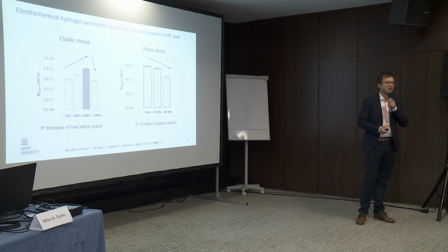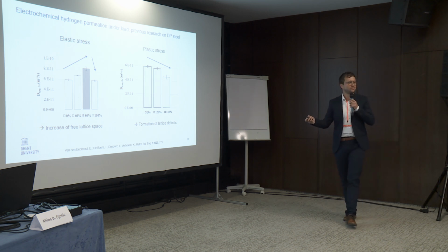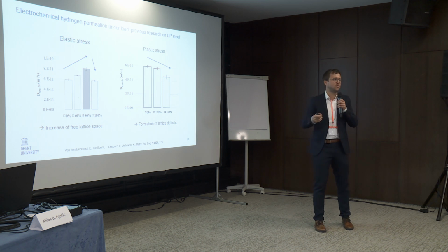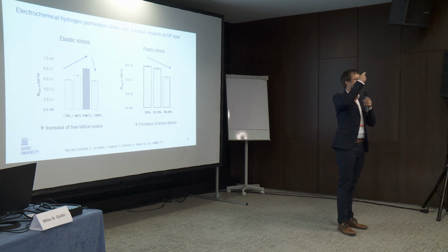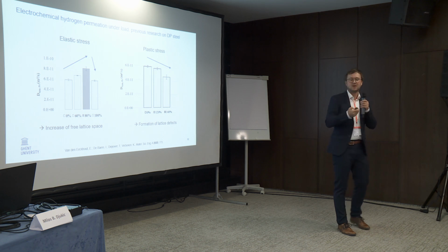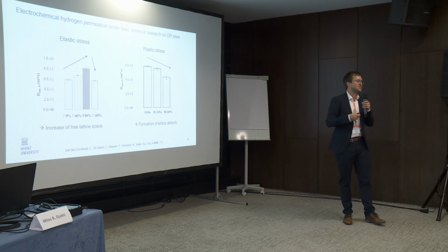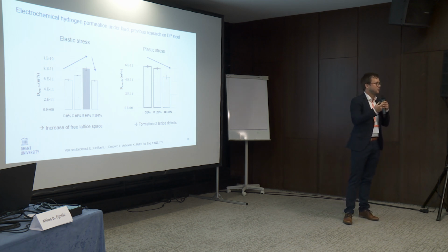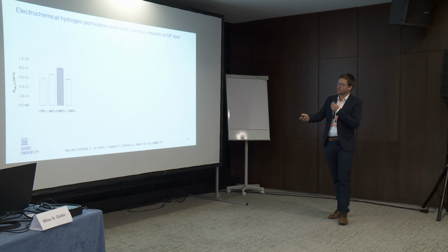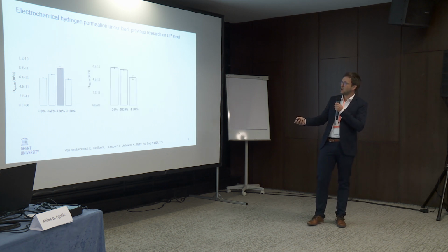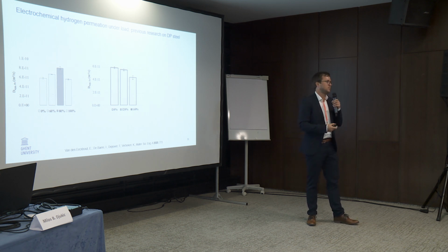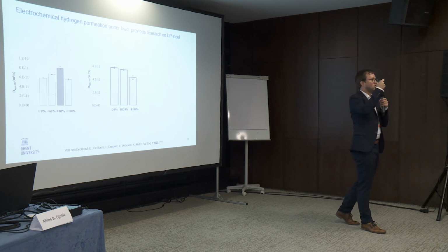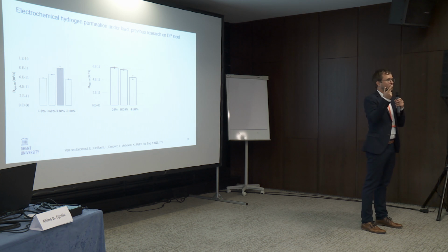dropping. However, this is during constant load. So for these situations you have both, because it's constant load and then you do permeation, you have the contribution of the elastic stress, but also the plastic stress. Both act at the same time. So to prove our point that the elastic stress is indeed accelerating diffusion, we also did the same. So this is just a repetition, elastic and then plastic. Plastic we decrease, but we also took the 120 sample, 120 constant load, so we have elastic contribution, plastic contribution.